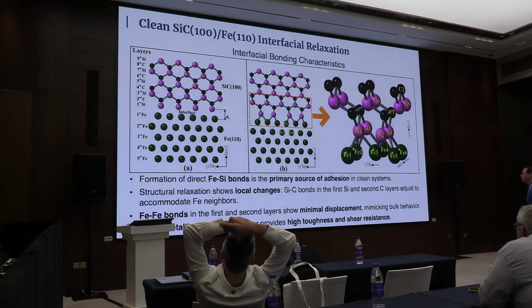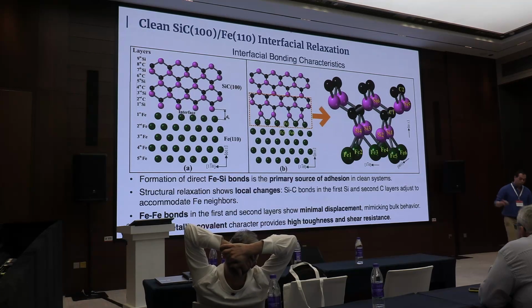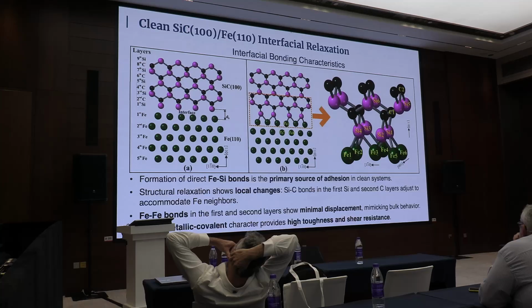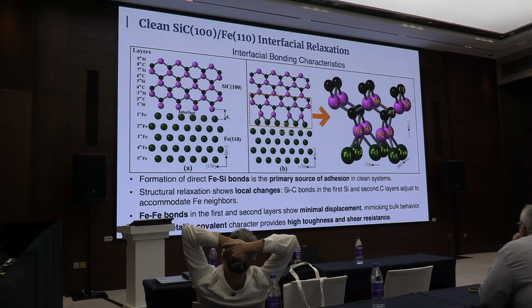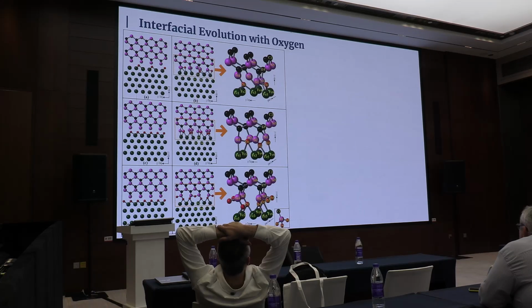So let's start to analyze the first one. When we relax the system without oxygen, the pure system, we observe that there is not much change in the second layers, and the change occurs all at the interface, as we observe there. So there is a strong relation between the systems, and we will study them: how the electronic interaction is, and how the distances between atoms are changing. So this is our reference for the rest of the computations. Then we add oxygen, more oxygen.